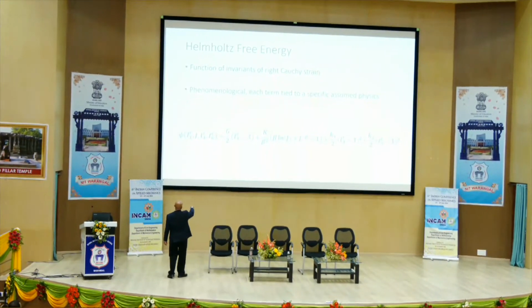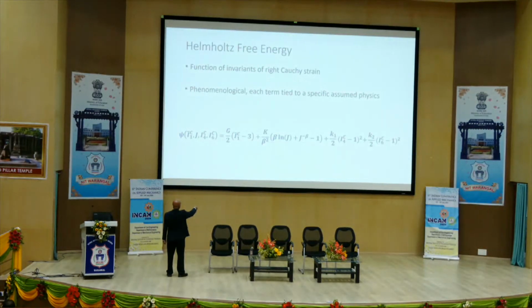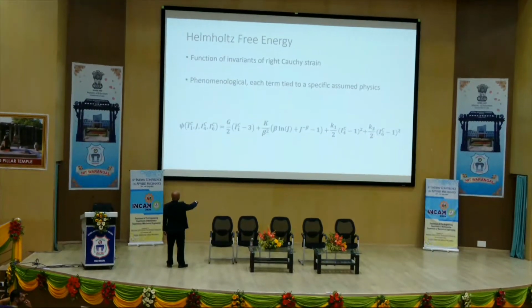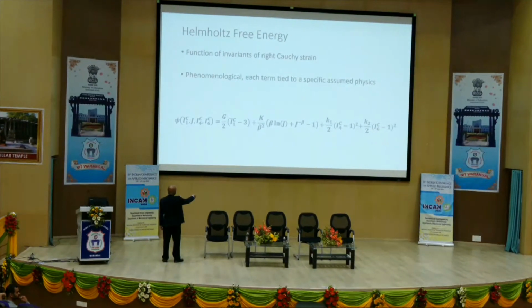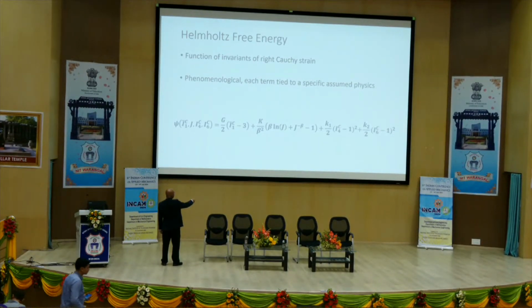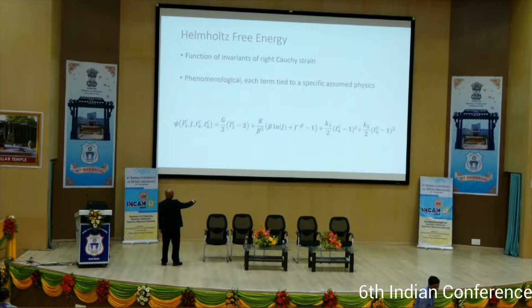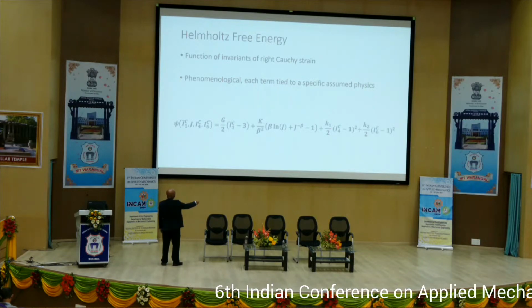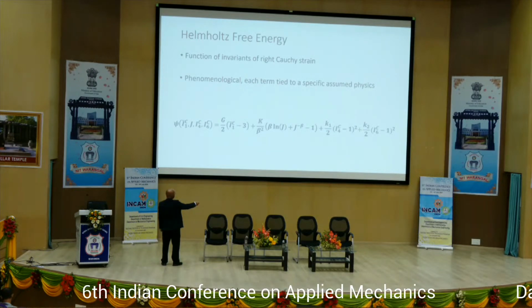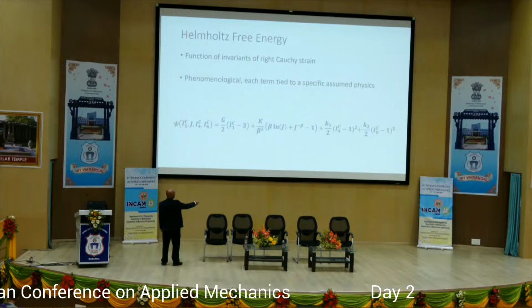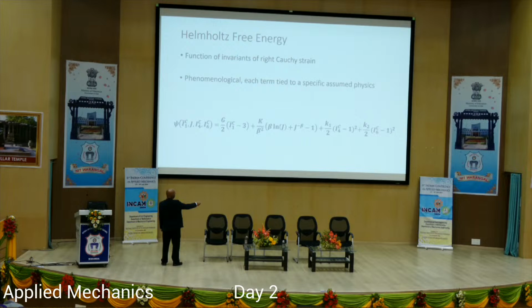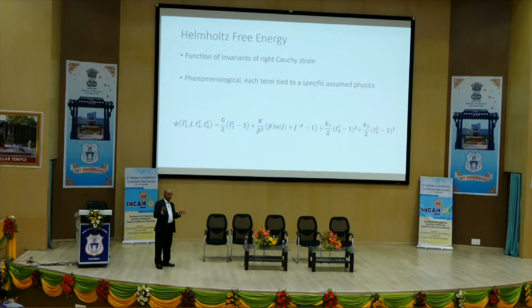So you can see the first term, shear modulus. Second term, bulk modulus. Since it's a hyperelasticity model, beta is the Ogden parameter. This term describes rubber-like elastic material where the stress-strain curve suddenly, after some strain, goes vertically up. So the beta captures that. J is the Jacobian, that is the volume. And this is the fiber. I4 is the invariant that describes the stretching of fiber system 1. Then the fourth term describes stretching of fiber system 2. But in most composites, they don't use two fibers, like S2 glass fiber and Kevlar fiber. They use only one fiber system. Because of that, the fourth term would disappear.